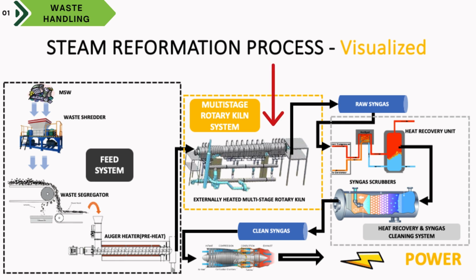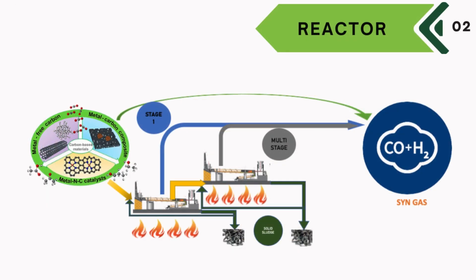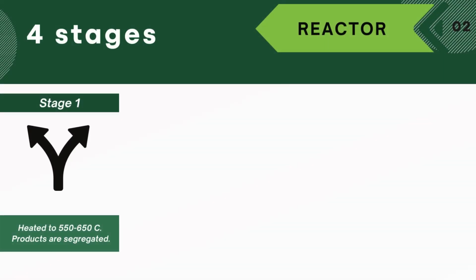At the kiln entrance, high-temperature steam is introduced continuously to purge the MSW of atmospheric air, nitrogen and oxygen, and to prevent the conversions to toxic and undesirable nitrogen oxides, NOx, and/or other oxidized products. The rotary kiln reactor is where the steam reforming reactions occur. The first stage kiln is heated externally to a temperature range of 550 to 650 degrees Celsius to initiate the treatment, providing sufficient temperature, turbulent mixing, and residence time in the first reaction zone to achieve the target conversion levels, with any carryover metallic materials intact and residual carbon char formed.